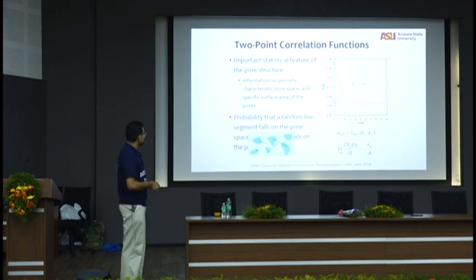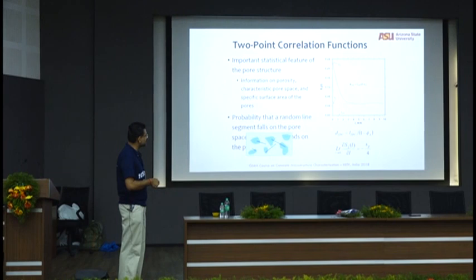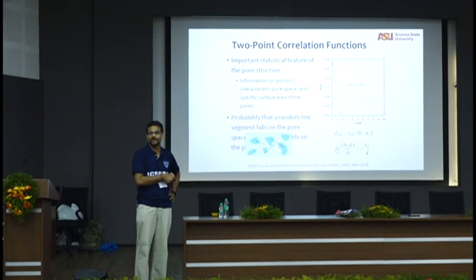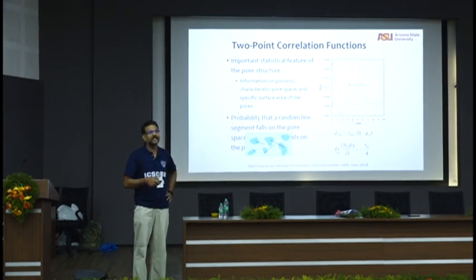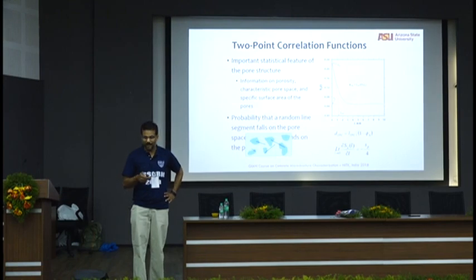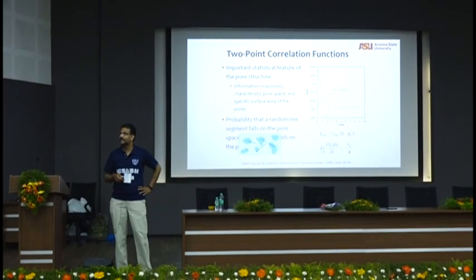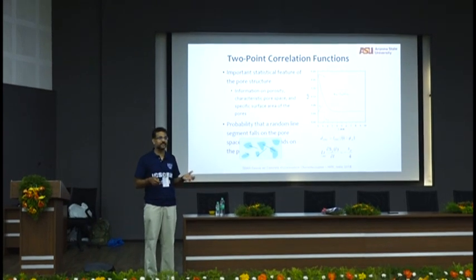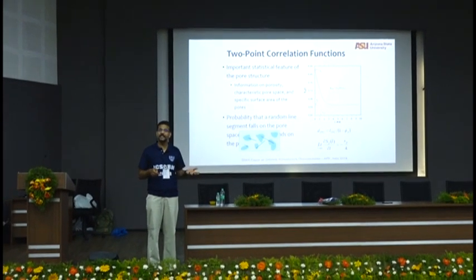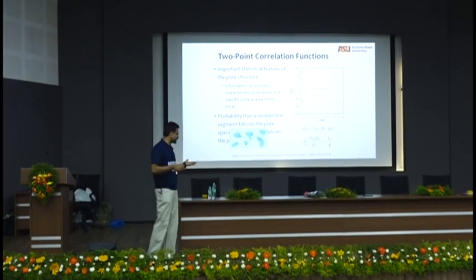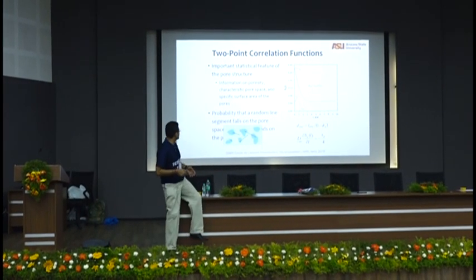Not done. You take the derivative of this function with respect to the length, and set the limit of L tending to 0, you get one-fourth of the specific surface area of the pores. Right? Specific surface area is extremely hard to determine otherwise. Now, image analysis and a little bit of mathematics gives you a way to find out the specific surface area of pores. And specific surface area is important in a lot of different things. Can you give me one example where the specific surface area of pores is important?